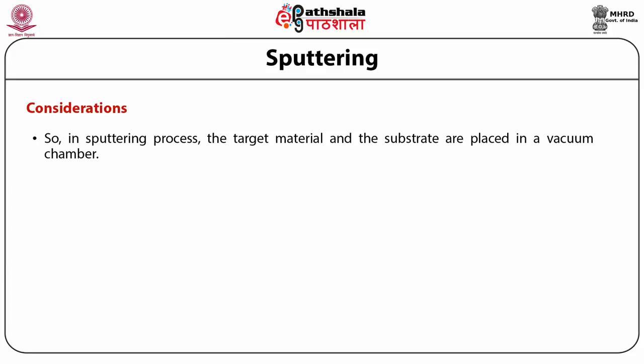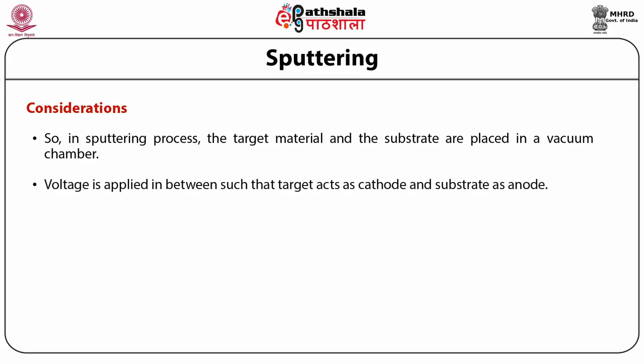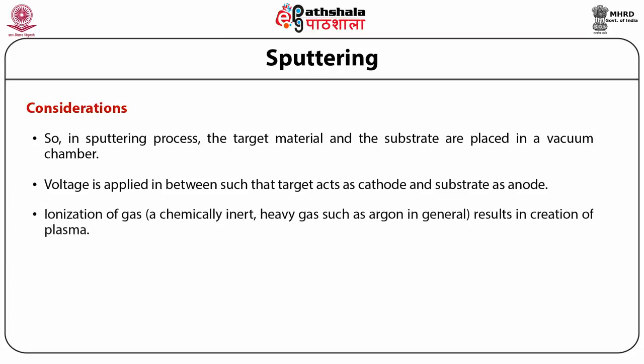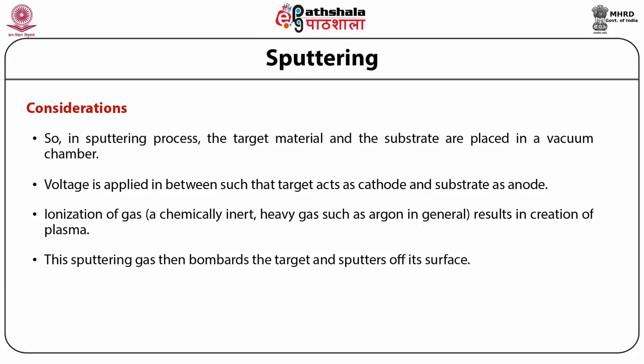So in the sputtering process, the target material and the substrate are placed in a vacuum chamber. Voltage is applied in between such that the target acts as the cathode and the substrate as the anode. Ionization of a gas, a chemically inert heavy gas such as argon in general, results in the creation of plasma. This sputtering gas then bombards the target and sputters off its surface.